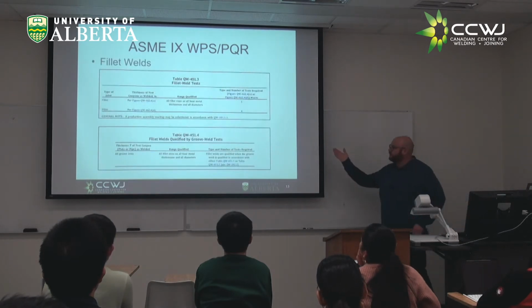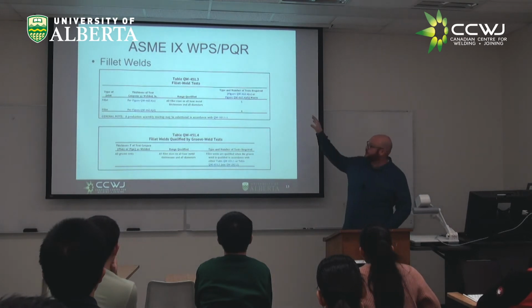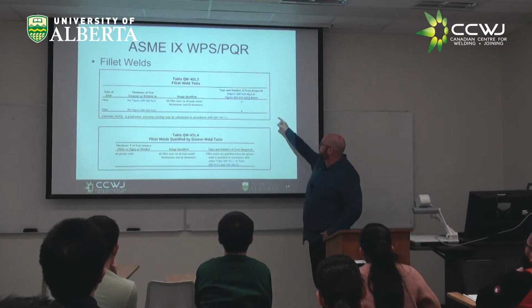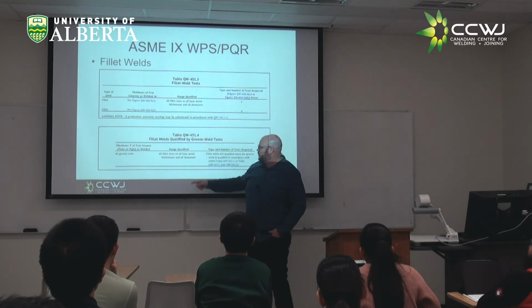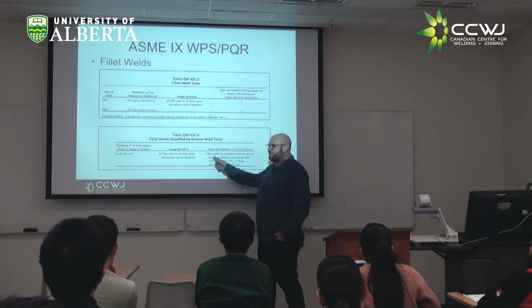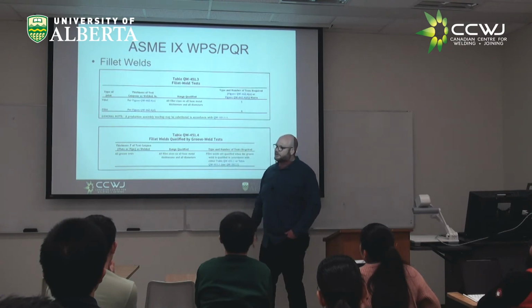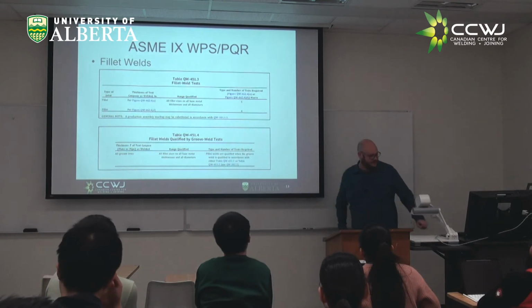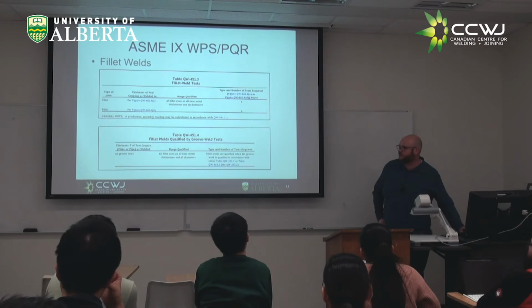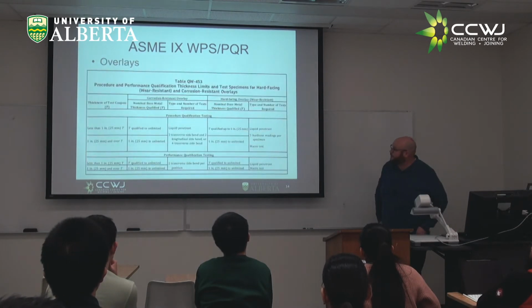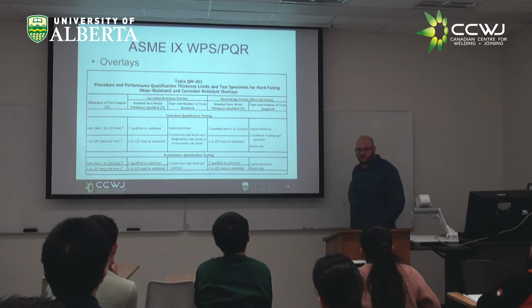So you can qualify. There's a separate qualification if you just want to do fillet welds. But you can see there's a bunch of tests and you have to go through a bunch. But if you do it through a groove weld, you're qualified for everything just by doing one groove. So that's just the way ASME approaches it, is they don't give fillet welds that much stick. Similarly, if you're doing special processes like corrosion resistant overlays or hard facing overlays, there's a separate qualification scheme